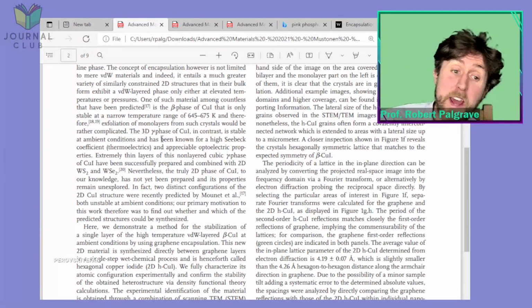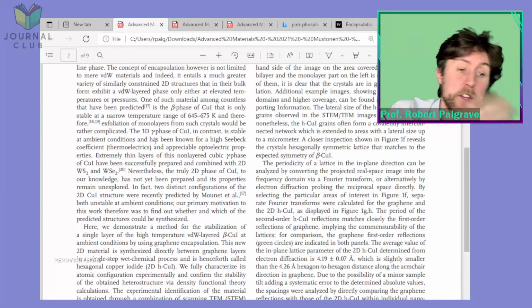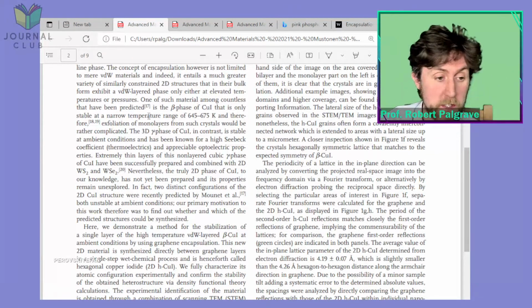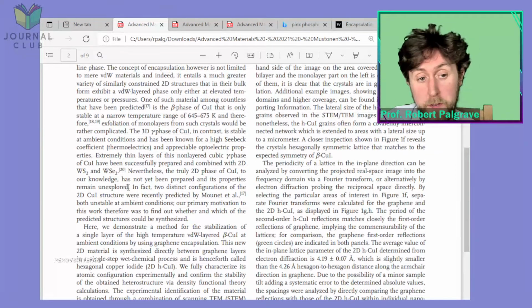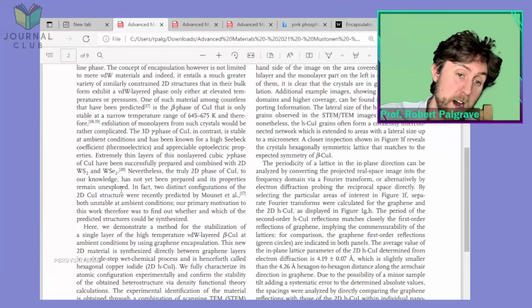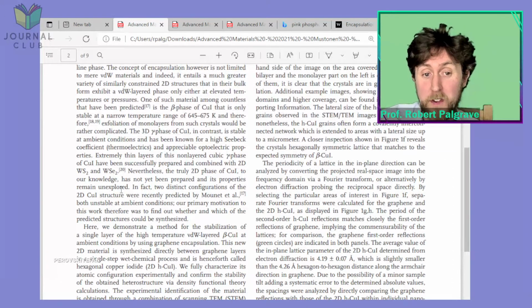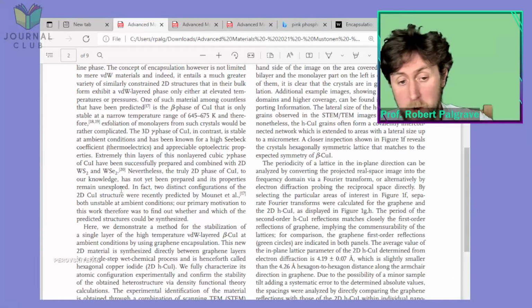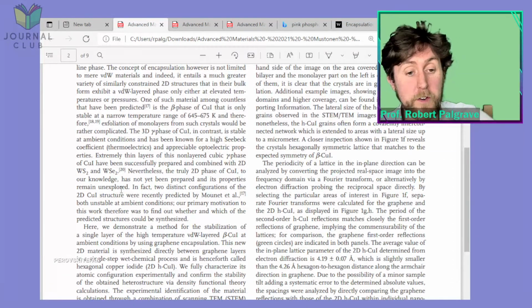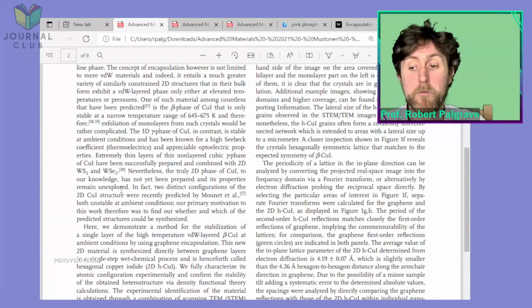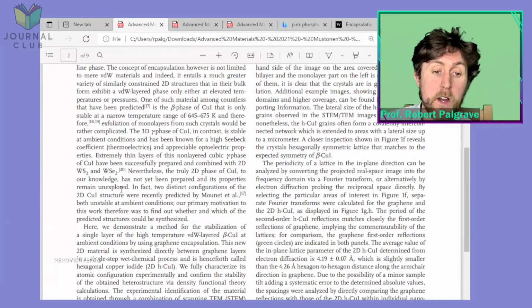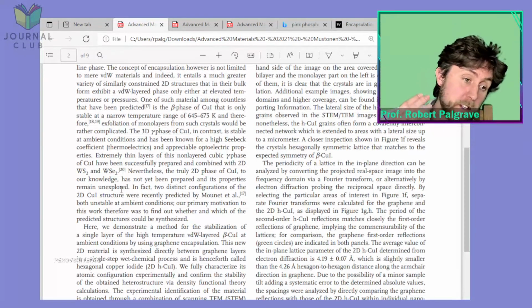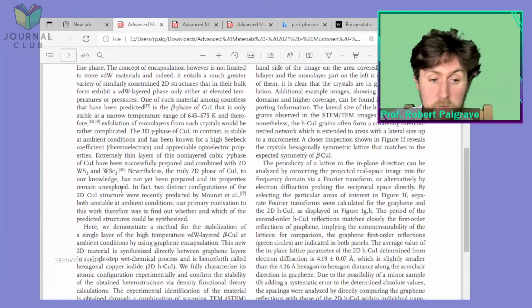But the layered form, in theory, could be exfoliated and made into a 2-dimensional material the same way as graphene, the same way as the transition metal dichalcogenides that they mention here. And the challenge, though, is that it's only stable at high temperature, so 645 Kelvin, pretty high temperature to be doing these experiments. Could be some practical difficulties in doing that. Probably not impossible, but there's practical difficulties. So they're looking for a different way to stabilize this material at room temperature.